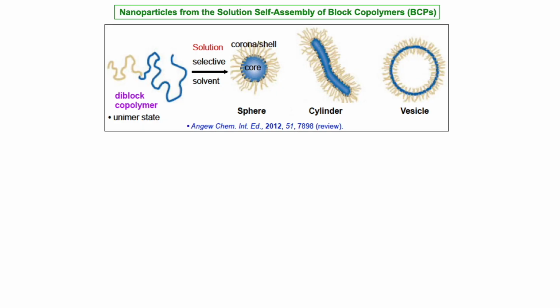So what you have is called a block copolymer now. Instead of a surfactant, you've got a hydrophobic part in blue, a hydrophilic part in orange, and these are long chains. So when you put them in a solvent that's good for the orange part but bad for the blue bit, you get micelles, but these now are much more stable.